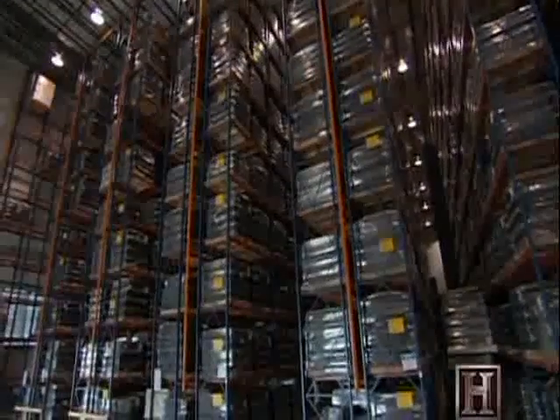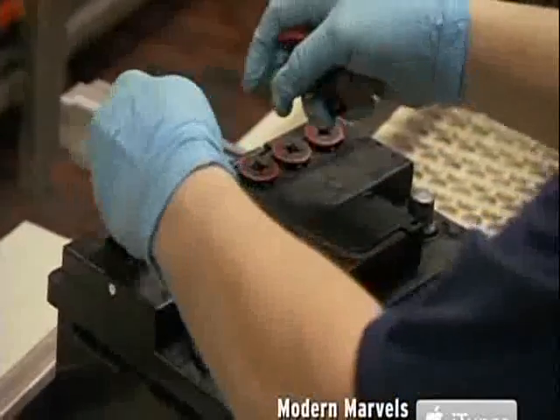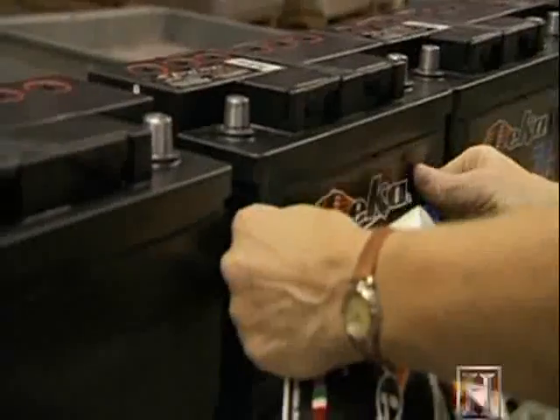The nearly completed batteries remain in storage until it's time for the company to fulfill its orders. Only then are the batteries filled with the electrolyte solution that is 2/3 water and 1/3 sulfuric acid. After the batteries are filled with electrolyte, there is no voltage there until we bring them into this forming room where they are hooked up and electrically charged to form the batteries. Once they are formed, they are a 12-volt battery, which then will be taken to our finishing department where we top the batteries off. We plug the batteries, we wash them, we brush the terminals, we put a high voltage rate test on them, and then they are labeled for our customers.